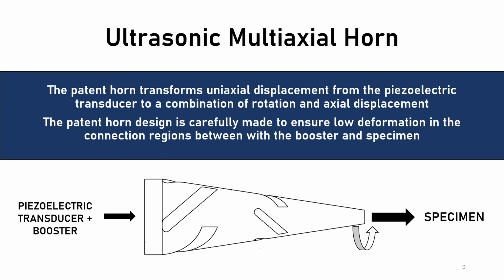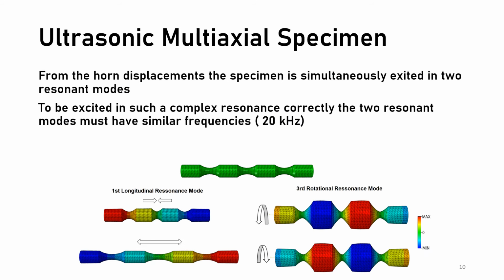What enables the torsion simultaneously to the tension and compression is a special patent horn we apply in our design. Here the horn transforms the axial displacement coming from the booster and the piezoelectric transducer into a combination of rotation and axial displacement that is transmitted towards the specially designed specimen. Because the specimen receives the two types of displacements in phase, the rotational and axial displacement, the specimen needs to be specially designed to be able to enter in resonance in two different modes, one for the axial displacement and one for the rotation.